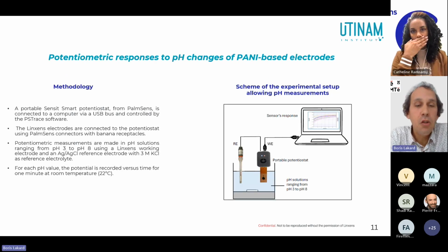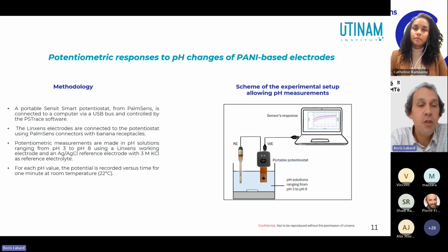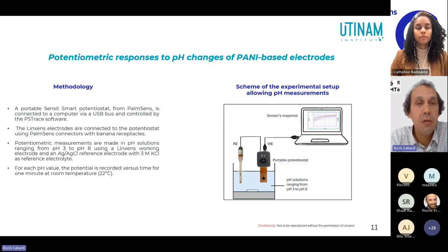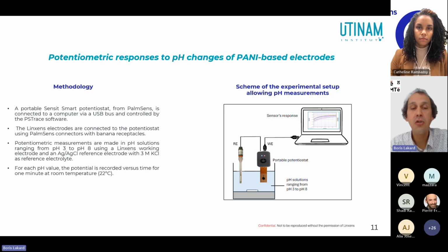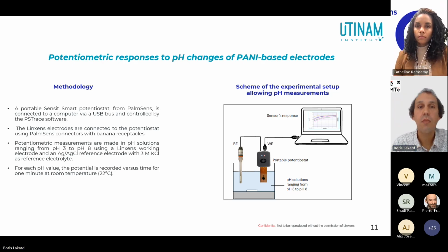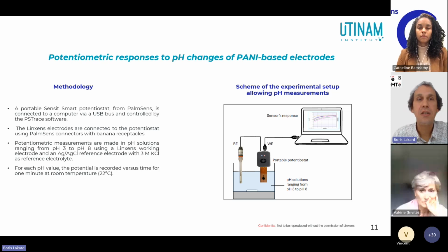I'm now going to talk about the potential measurements for pH calibration. These measurements were carried out using a PalmSens portable potentiostat. The measurements were performed between Linxens polyaniline-coated sensors and a reference electrode. For each pH value ranging from pH 3 to pH 8, the potential was recorded as a function of time for 1 minute. You can see the description of the experimental setup on this slide.